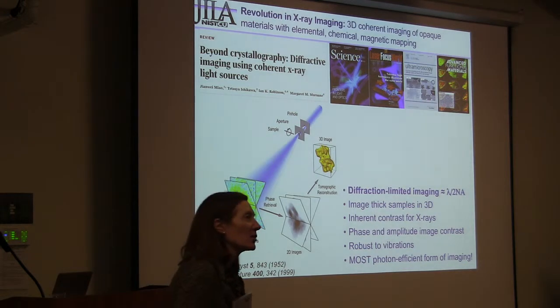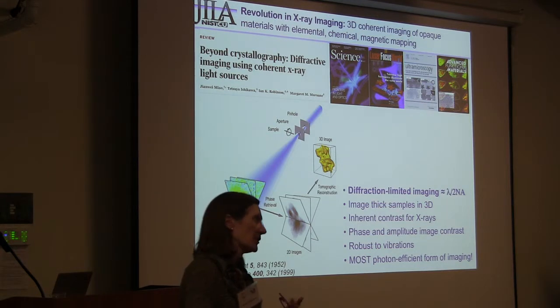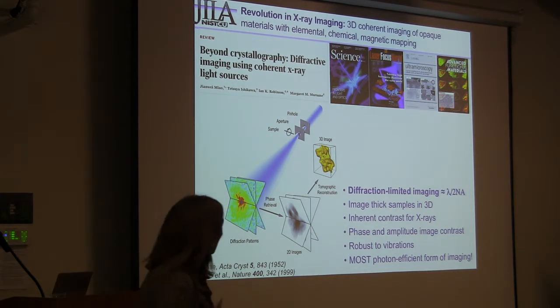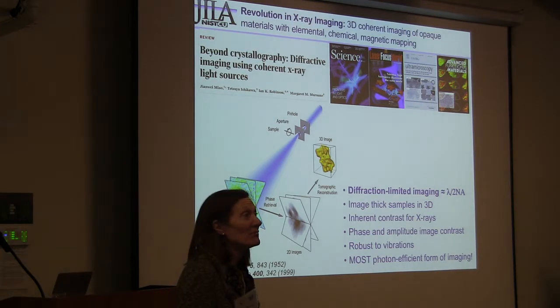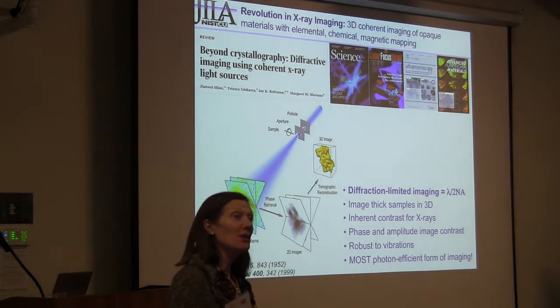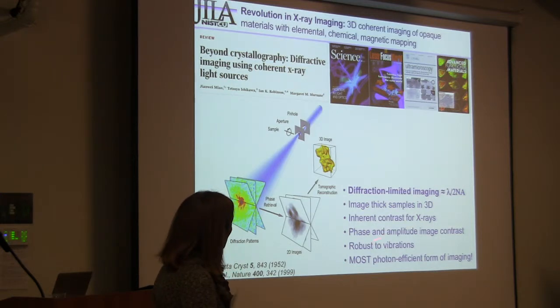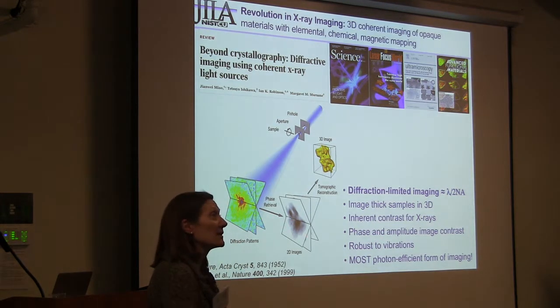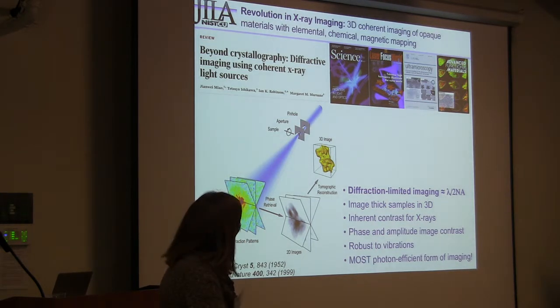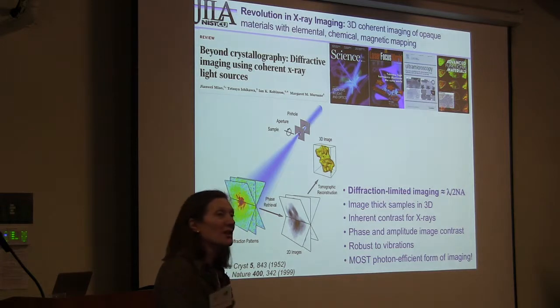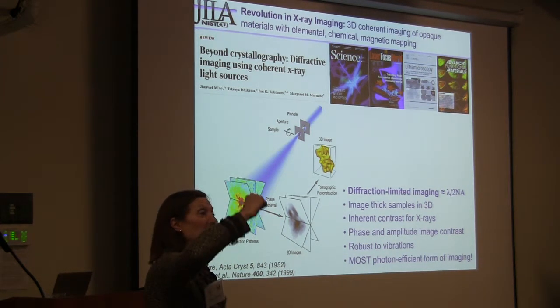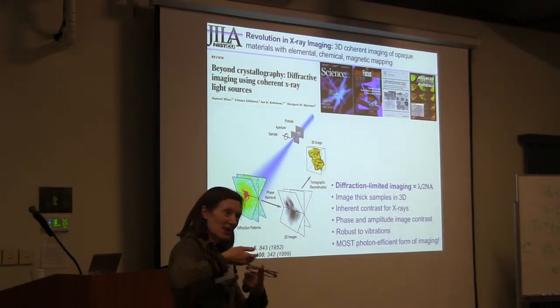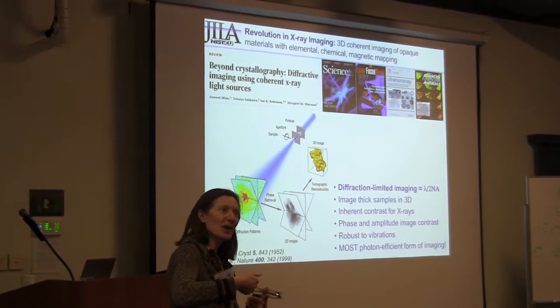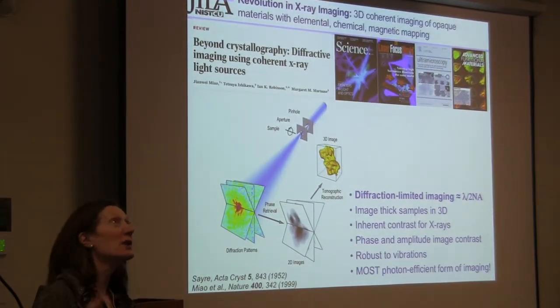And why is this really interesting for all kinds of X-ray sources, the free electron lasers, the synchrotrons, and the harmonic light sources? It's that you can get to diffraction limited imaging. So you can get to half the wavelength. You can image in 3D. You get a phase and amplitude image of your object. It's robust to vibrations because the CCD pixel sizes are on the order of, let's say, 13 microns. So you only have to stabilize your sample and illumination to make sure that the light doesn't move from one pixel to another. And that's much less constrained than having a positioning tolerance of a few tens of nanometers and a spot size of 10 nanometers. So it's three orders of magnitude easier.